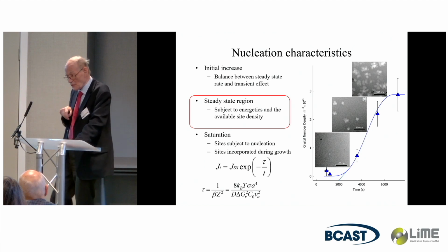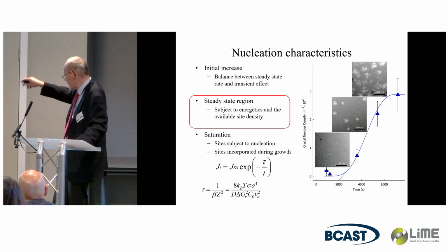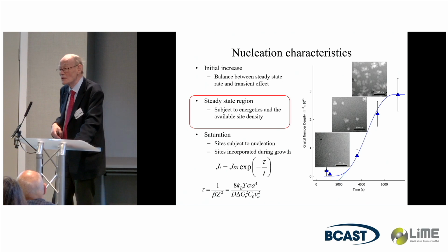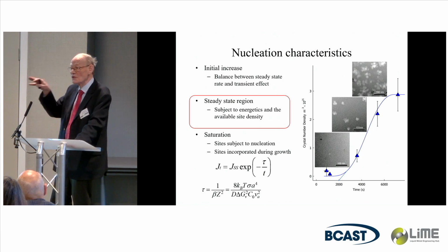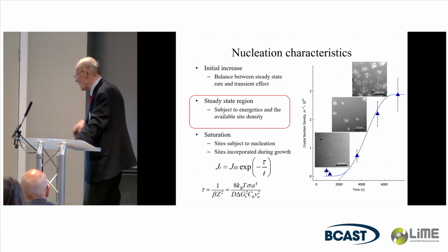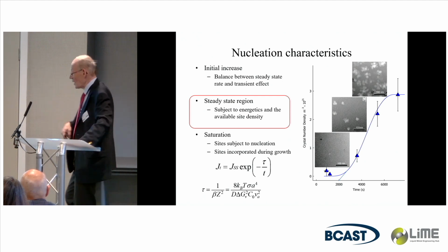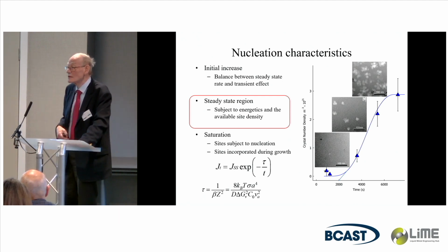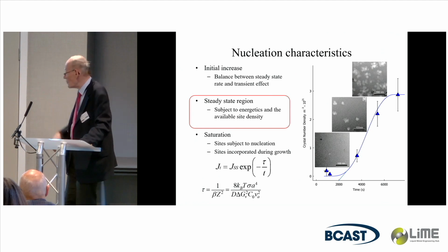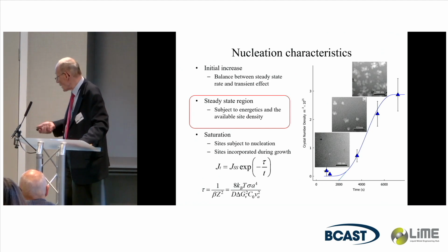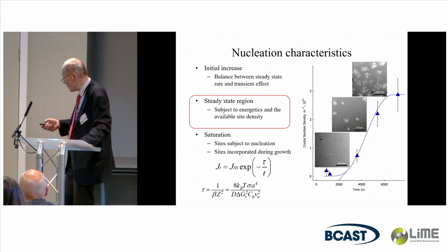In other words, you put your sample in and start annealing. There are no nanocrystals that form initially. It takes some time before the first ones appear. This is a delay time. And so this tells us we have transient nucleation. That's very important. And that actually is the main reason that this forms a glass. And so we had to measure the delay time.